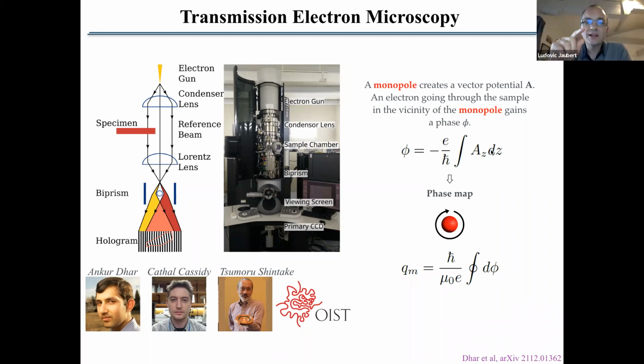Well, that would be true if you didn't have these magnetic dipoles. From the point of view of the emergent gauge field, you are correct. If you only have the emergent gauge field, you will not have a real effective magnetic field, and so you will not have a real vector potential A. But the thing here is that in spin ice, and in the sample that we're going to talk about now, the emergent gauge field is, to a good approximation, the same as the real magnetic field H in the system.